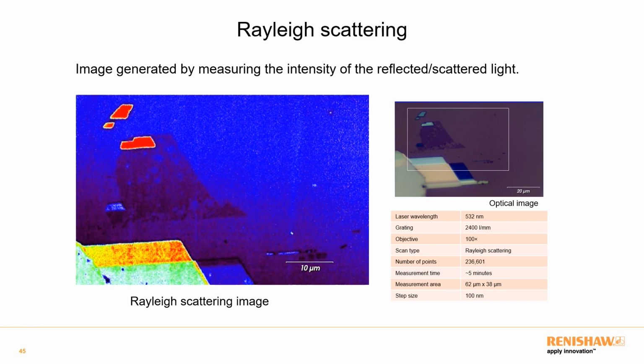And what we can see here are a couple of things which are of interest. The first thing is our substrate is primarily blue. It changes to a slightly purplish as we go through. This is because here we're looking at the intensity, so any deviation in focus is affecting our Rayleigh scattering. So when doing Rayleigh scattering, it's really important you maintain sample focus.